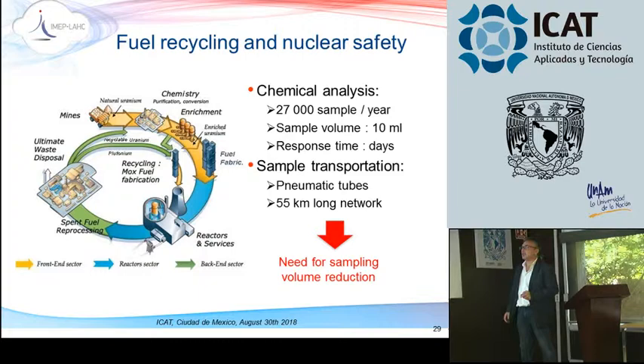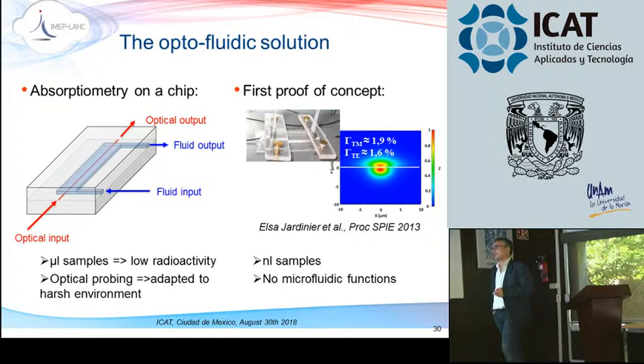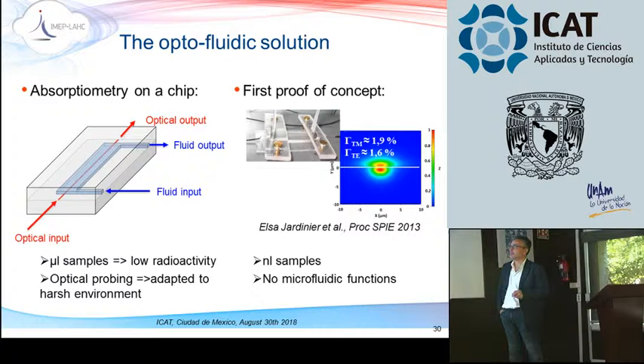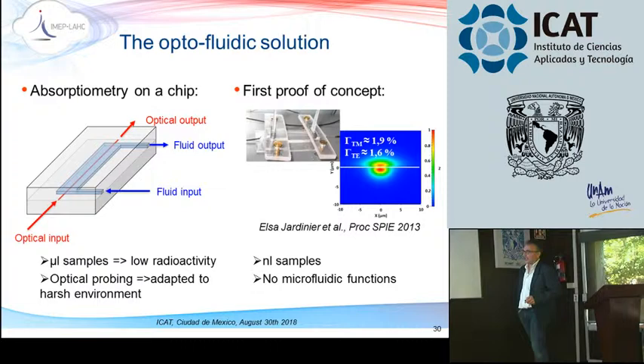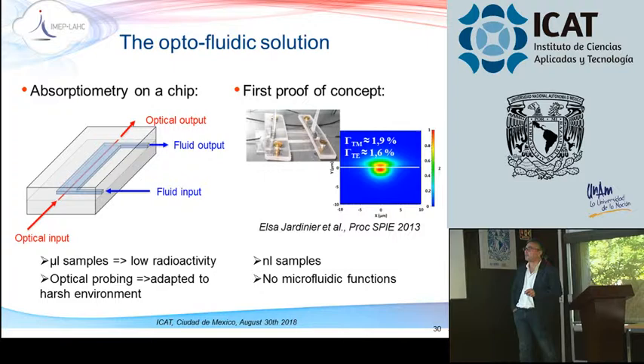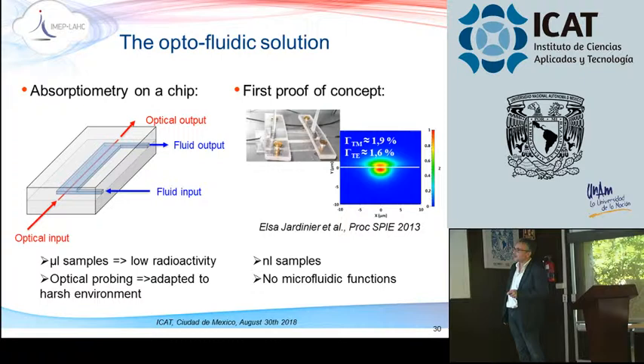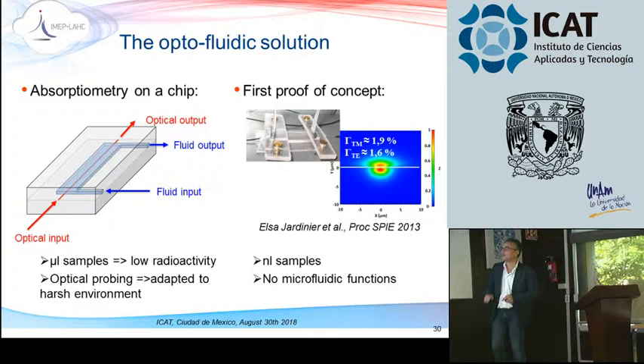So the idea, what we proposed, the principle, is to have a microchannel here with an input fluid, an output, and then an optical channel, and we will just measure the absorption due to plutonium and see the concentration. So we made a first test. You see, it's really a proof of concept, something you can do in the lab. And we designed a waveguide in such a way that there is a huge interaction between the waveguide that is here and the nanochannel that is here. The channel here is only 100 nanometers thick, so it's really small. So we reduce the volume.